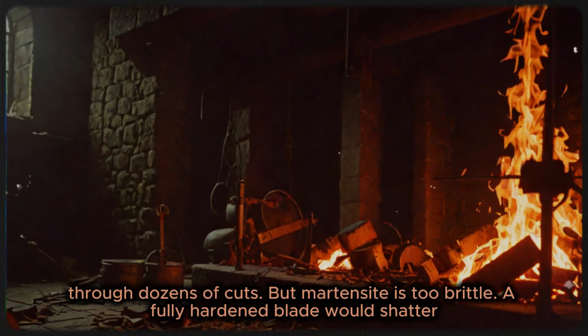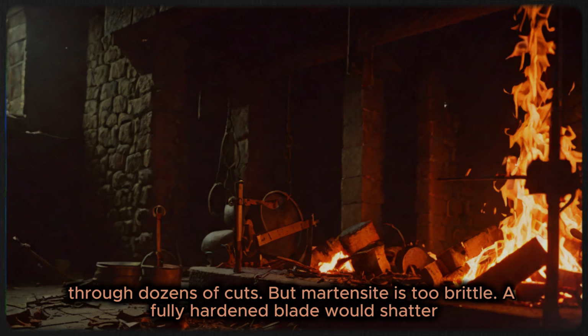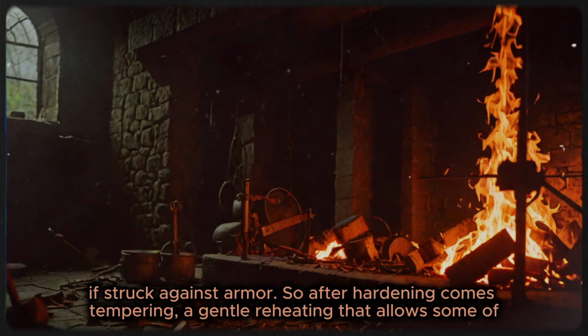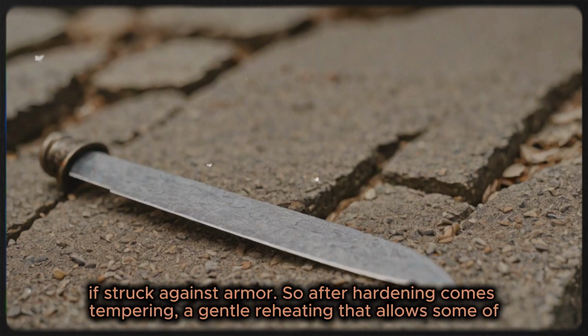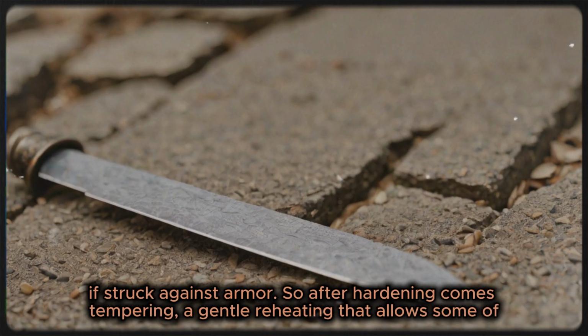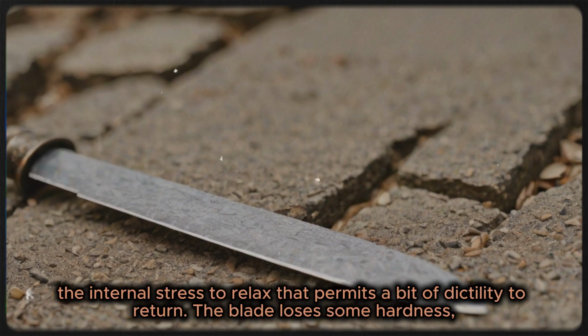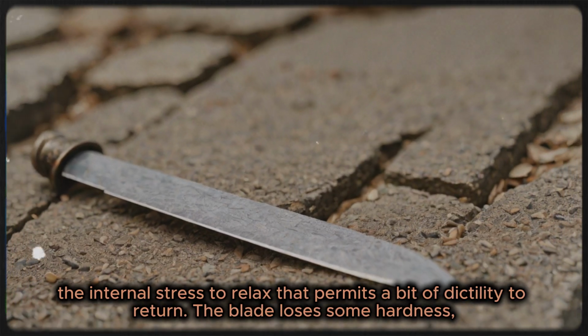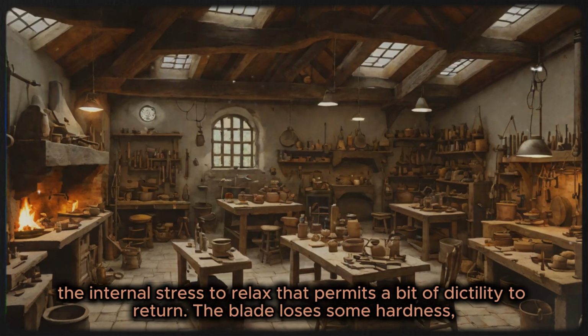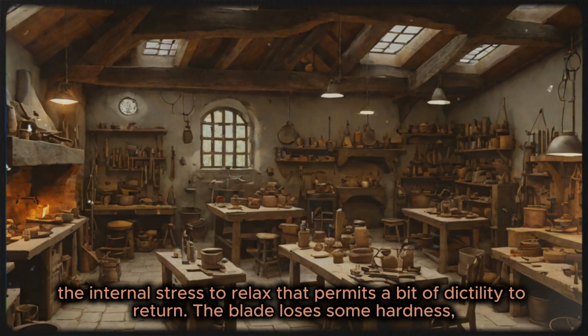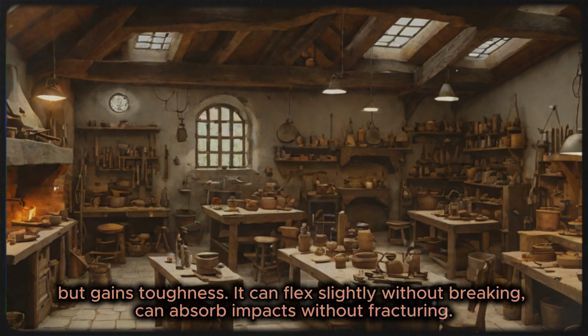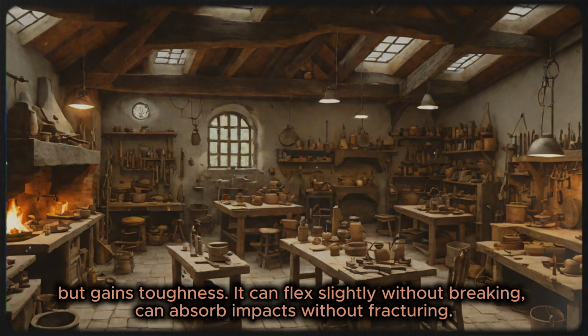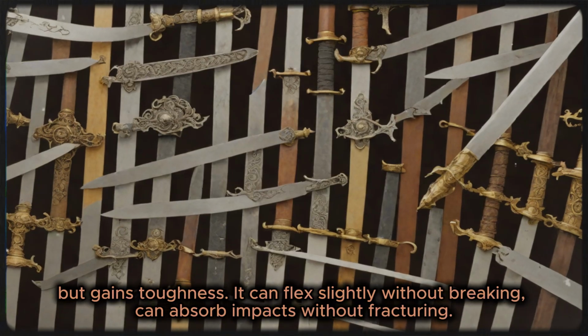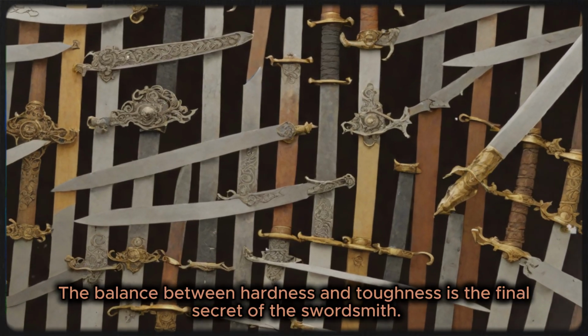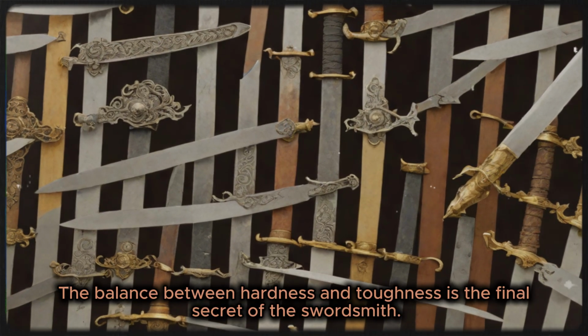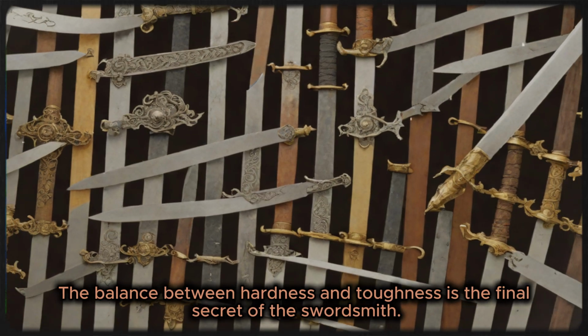But martensite is too brittle. A fully hardened blade would shatter if struck against armor. So after hardening comes tempering, a gentle reheating that allows some of the internal stress to relax, that permits a bit of ductility to return. The blade loses some hardness, but gains toughness. It can flex slightly without breaking, can absorb impacts without fracturing. The balance between hardness and toughness is the final secret of the swordsmith.